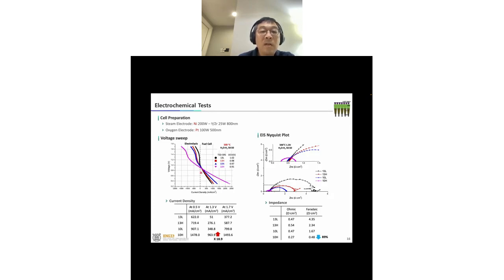So this is zero current density. On your right side, we are providing hydrogen and oxygen and making electricity. You can see it generates up to about 2 amperes, which shows very high performance even at 500 Celsius. It's a thin film structure, and it really works at very low temperature, and it's stable. On the left side, we're providing water and making hydrogen. So it's electrolysis mode.